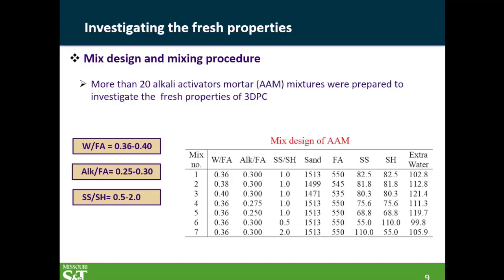We looked at a lot of mixtures. We did machine learning as well to optimize some of the mixtures, and ended up with those 7 mixtures that we are going to focus on today. Those 7 mixtures have different characteristics. Water to fly ash ratio up to 0.4. Alkali to fly ash ratio about 0.3. And then sodium silicate to sodium hydroxide moving from 0.5 to 2.